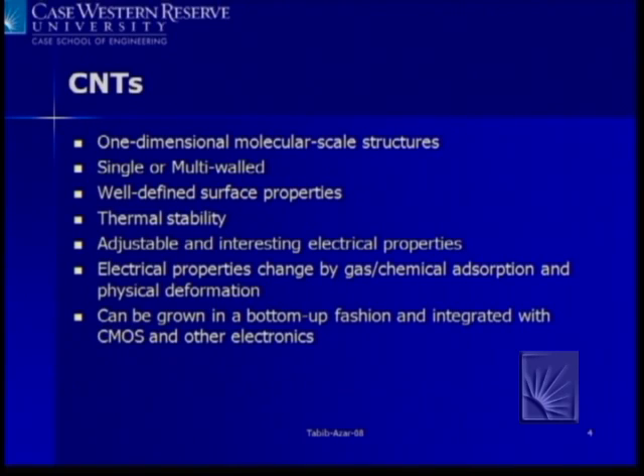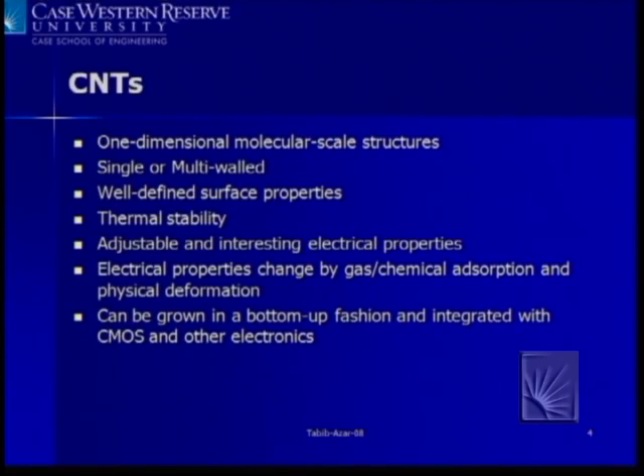They're extremely stable. All the carbons in carbon nanotubes are very happy to be there, and they don't have dangling bonds. Therefore, they don't oxidize easily unless you want them to. So at room temperature and in a normal environment, they don't oxidize, and they're pretty stable. And you can adjust their electrical properties by putting oxygen or hydrogen near them. So that's really good as far as their applications in gas and chemical sensors, but it's bad if you want to make devices using these carbon nanotubes that have stable characteristics. So you have to passivate them if you don't want them to sense things in the environment.